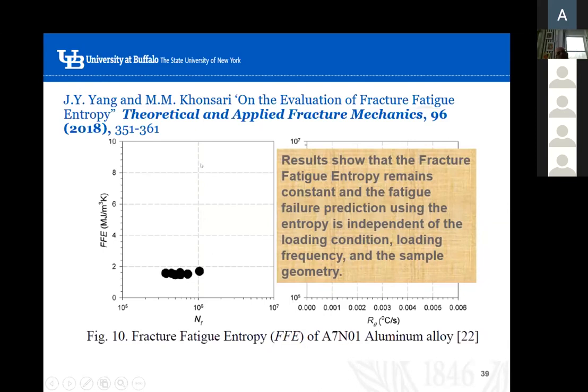Thank you. You're welcome. So here is another paper from Michael Khonsari's group at LSU, published in Theoretical and Applied Fracture Mechanics. Again, they tested aluminum alloy for different loading conditions, loading frequency, and sample geometry, different size samples. And then they plot the fatigue fracture entropy, megajoule per cubic meter at Kelvin, versus number of cycles. Now, the samples are breaking at different cycles, like you said, okay? So the fatigue life is changing.